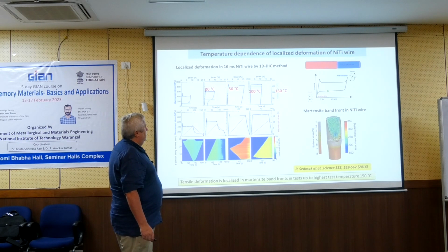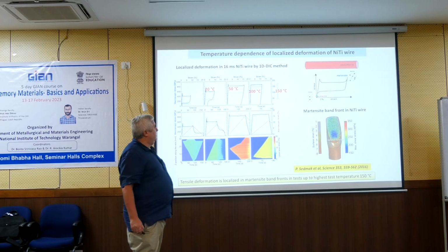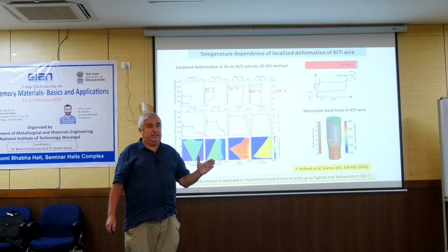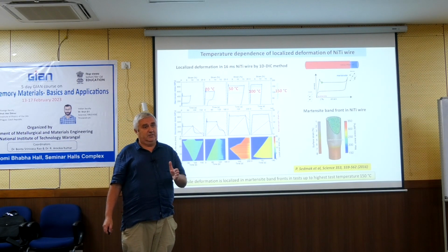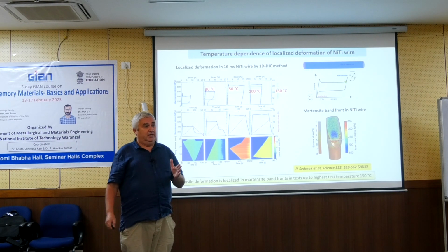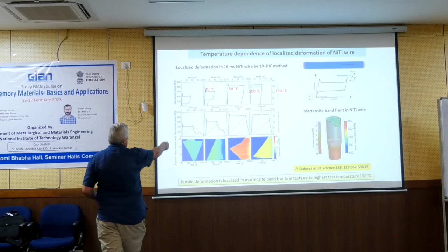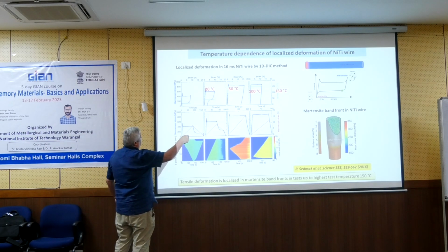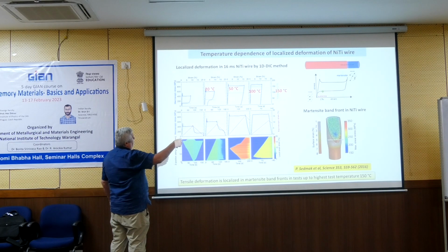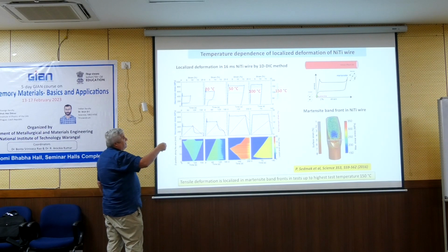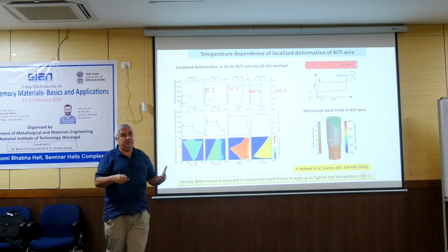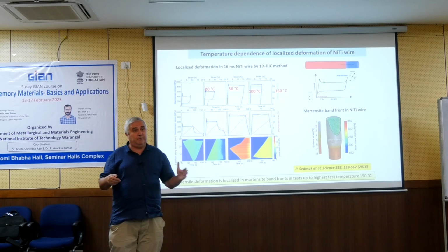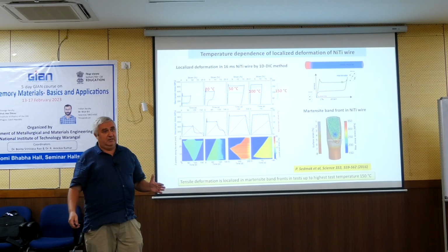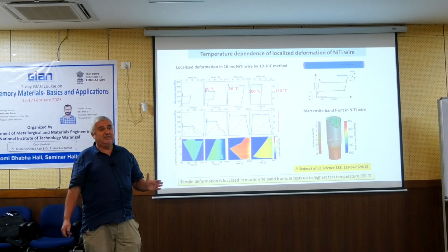After one complete cycle, there are no changes. There is always, no. If there is a martensitic transformation, there is always hysteresis. Yeah. So this has nothing to do with this plastic deformation. Only if there is plastic deformation, here some plastic deformation is over, the hysteresis is wider, but the hysteresis is here always. Hysteresis is here because of martensitic transformation. Even if it is completely reversible, you have hysteresis. Why do you think there is no hysteresis? Even with complete reversibility, you have hysteresis.